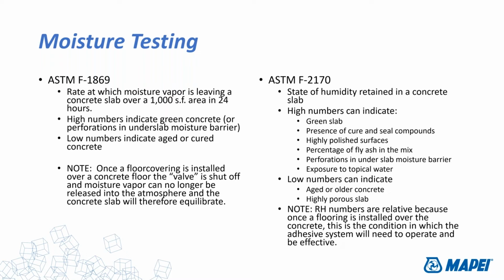Another cause is high polished surfaces. I've seen, and I'm sure many of you have seen, concrete slabs that are almost black and glossy, polished with motorized polishing equipment just to get a nice smooth surface. That's going to block up all the capillaries that allow moisture vapor emission to leave. That's going to keep it in the concrete slab and keep the RH high. Fly ash does the same thing.